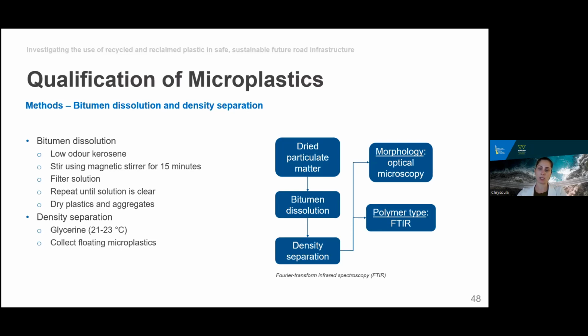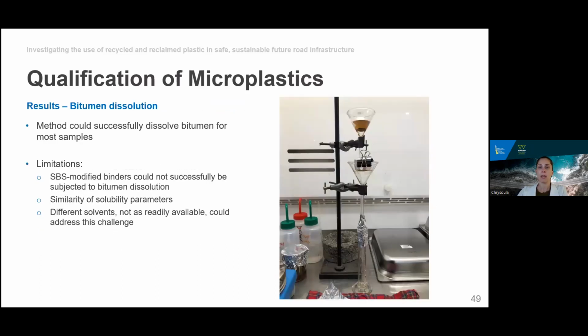The microplastics from this method could then be analyzed for morphology using optical methods, and polymer type using spectroscopic methods. We found that the method could successfully dissolve bitumen for most samples. SBS-modified plastics were an exemption due to the similarity of its solubility parameters with bitumen. For SBS, a different solvent or combination of solvents could address this challenge. However, we wanted to assess the method using solvents that are readily available in a bitumen laboratory. And that was just for this exercise here.